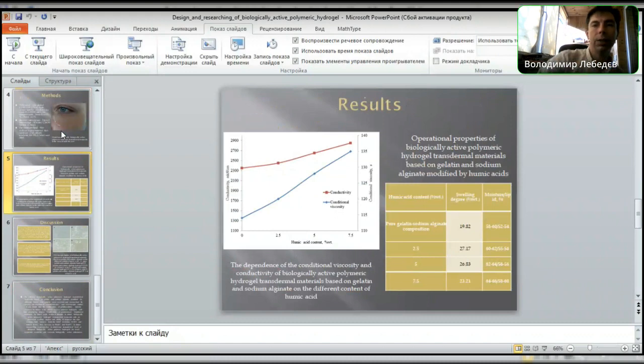In the first stage, for the biological active polymeric hydrogel transdermal materials based on gelatin and sodium alginate, we studied conditional viscosity and conductivity dependence on the different humic acid content. The results are shown in slide 5. Next, we carried out a study to determine the effect of modification by humic acid on the most important operation properties of biological active polymeric hydrogel transdermal materials, swelling degree, and effect on moisture-lipid balance measured of skin. As we can see from slide 5, the most characteristic changes are an increase in biological active polymeric hydrogel transdermal materials conductivity, viscosity, and specific electrical conductivity with an increase of humic acid content.